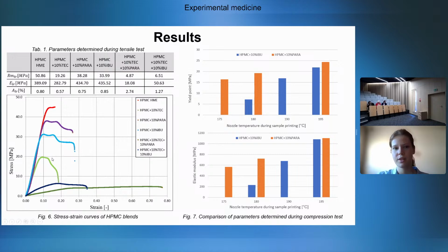As shown in figure 6, pure HPMC in red exhibits near brittle behavior, fracturing almost immediately after reaching plastic deformation, and has no easily distinguishable yield point. Blends containing either active ingredients or plasticizer were more ductile and deformed plastically. Their uneven curves, shown here, suggest that the samples were cracking while they were being stretched. Some brief strain hardening can be observed in both samples containing APIs, here and here.